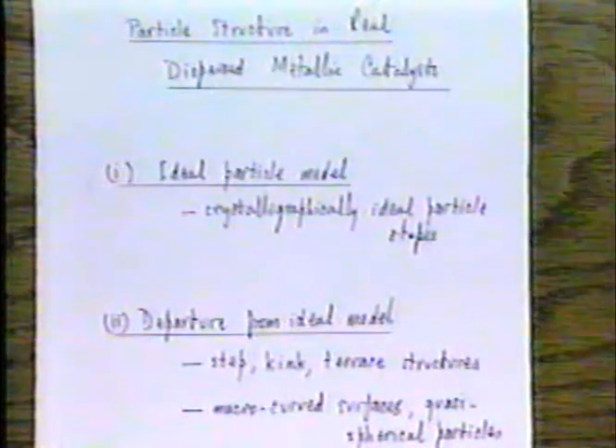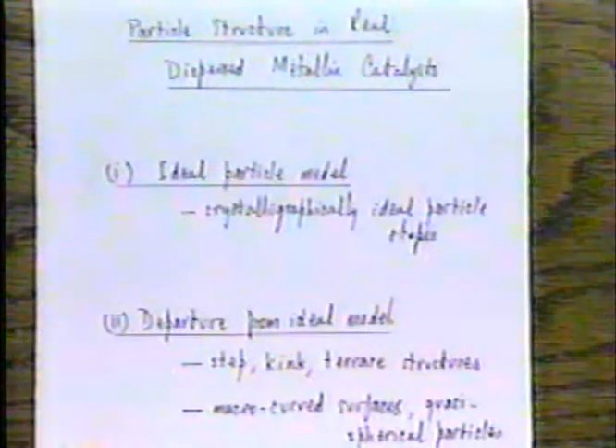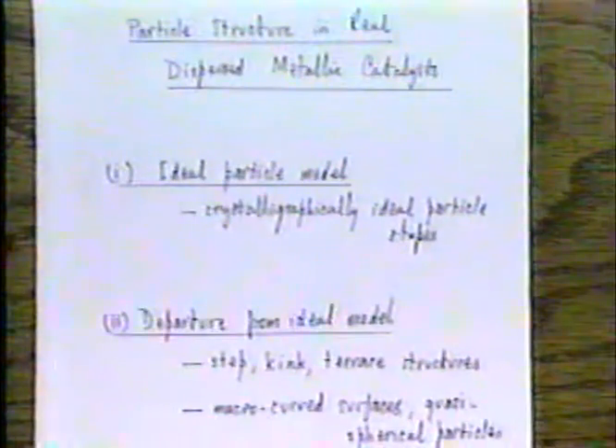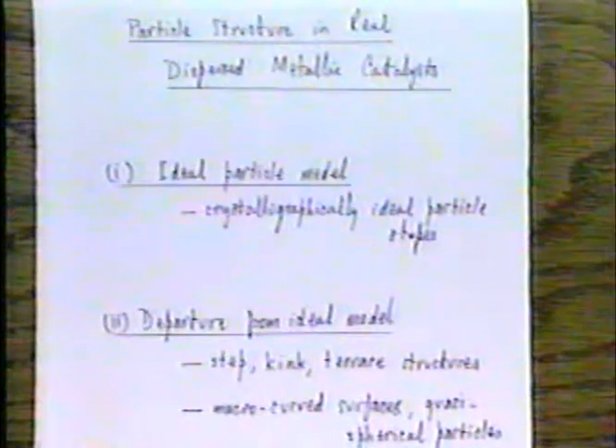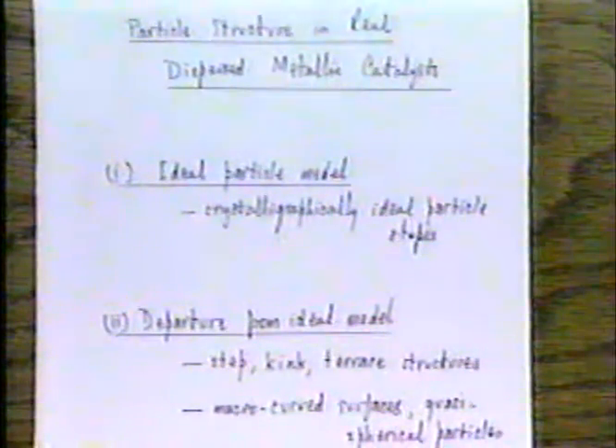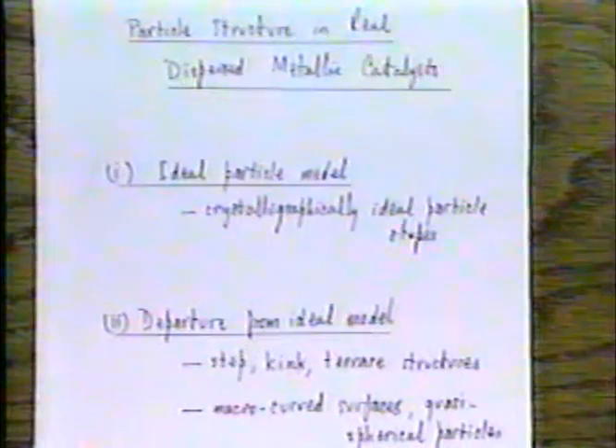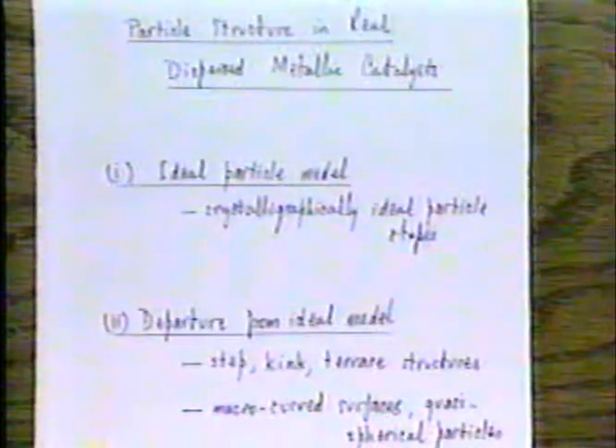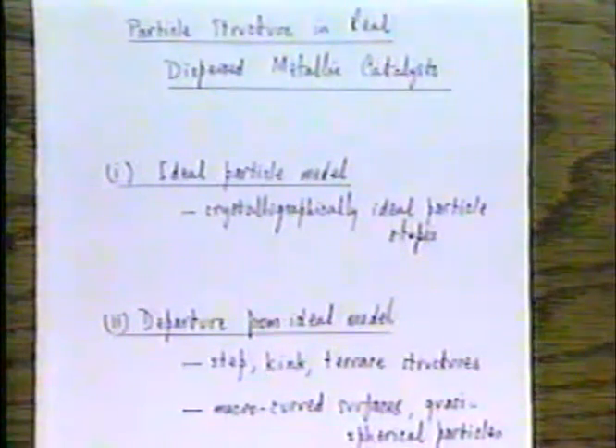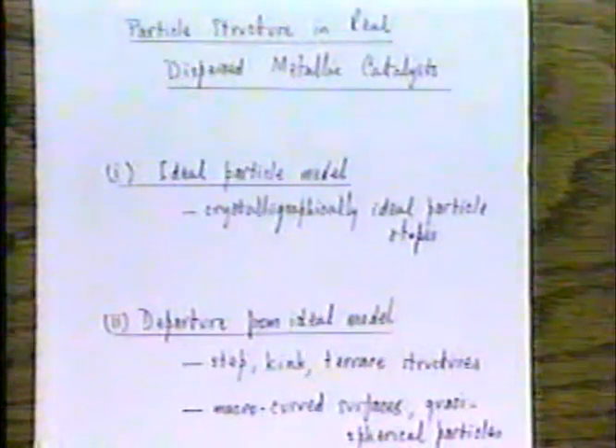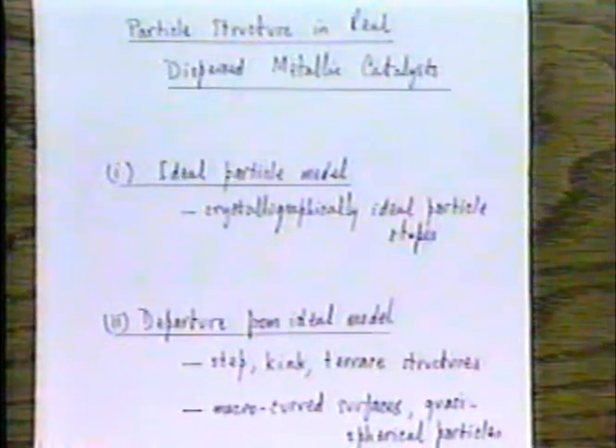But in certain special cases, not of the style we've been talking about, but often in vapor-deposited metal, particularly when it's deposited on a single crystal such as cleaved mica, or say the hexagonal surface of sapphire, you can get particles, small metallic crystals of ideal shape. It might be octahedrally shaped particles or whatever. But even those are usually only found and can only be characterized when they're in excess of 100 or 200 angstroms in size. And most of the particles which one is dealing with in supported metal catalysts are a good deal smaller than that.